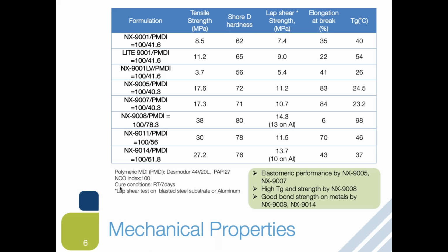So on this slide, these polyols are simply cured with the polymeric MDI at the isocyanate index 100, so theoretical mixture. And we cured them at room temperature for 7 days and collected tensile, Shore D, lap shear, TG, and elongation. From this study, what we learned is that elastomeric performance can be achieved by NX9005 and NX9007. And if you're looking for high TG, high strength like epoxy, NX9008 can offer those performances. And if you're looking for excellent bond strength on metals, including aluminum, NX9008 and NX9014 can provide those performances.